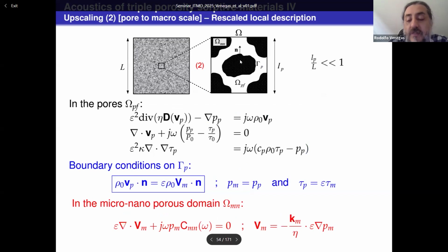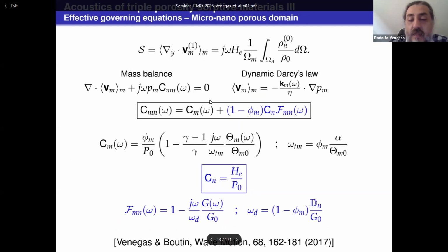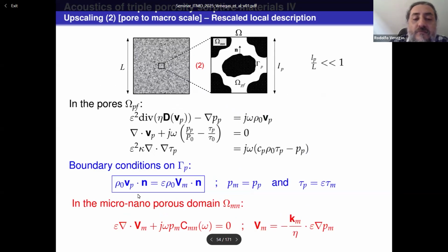What we have just derived here is formulated in the grain. And this is shown here. The boundary conditions between these pores and these grains on gamma p are continuity of mass flux and continuity of pressure and temperature. In particular, as previously, this is showing that the mass flux generated or pulled from the macro for this porous grain is much smaller than the mass flux generated by the carrying wave around these grains